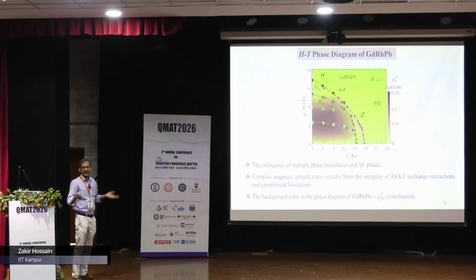From all these data, susceptibility, heat capacity, resistivity under magnetic field, we draw this phase diagram. And this region is where the topological Hall effect appears. So we believe that in this region of the H-T phase diagram, the magnetic texture is such that it produces topological Hall effect. So again, neutron diffraction and ARPES will be good for this compound.